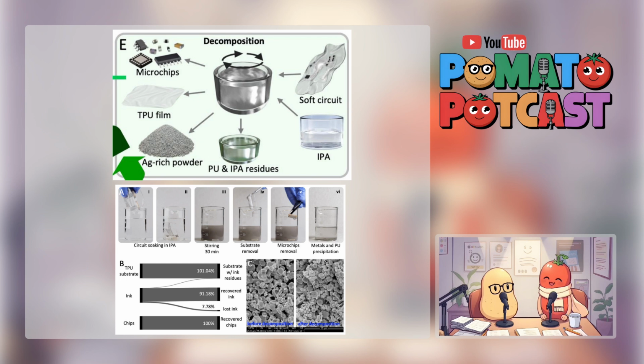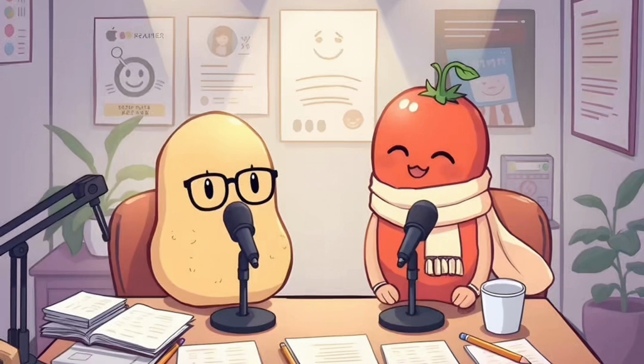Do you lose much silver doing that? There's about a 20% loss of the ink material during that washing step to purify the silver. But the recovered silver itself can then be used to make new ink. And is the recycled ink any good? Remarkably good. Its conductivity was only slightly lower than the original ink, like a 2.4% decrease. That's barely anything. Any downsides? It did lose some of its stretchability after recycling, so maybe not quite as robust for extreme bending applications the second time around, but still very functional.